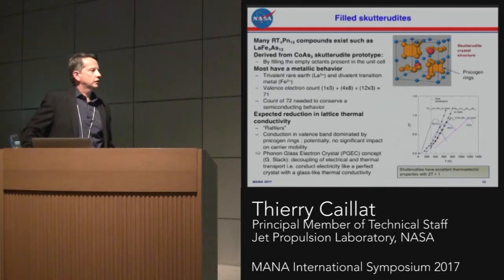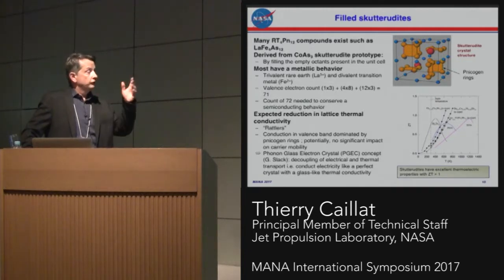One of the classes of materials that we have focused on is the skutterudite materials. It's a cubic structure, and one of its features is that it has two large voids inside the structure that you can fill with different rare earths. That's a very powerful tool to tune both the electrical and thermal transport properties. If you put a rare earth in this, you end up with basically a semi-metal, which is where we want to be in terms of thermoelectrics anyway, so that's good.